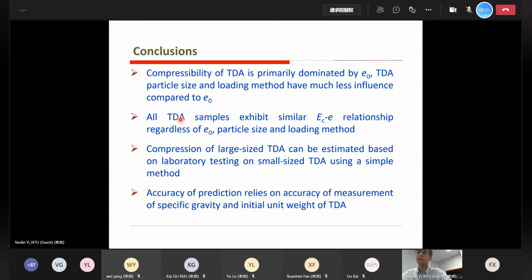And second, all the different types of TDA samples we studied have almost the same compression modulus and void ratio relationship, regardless of initial void ratio, particle size, and loading method. So this is very useful for practice. We can use this to estimate the compression of large-size TDA based on the results of small-size TDA in the laboratory. So it's possible to apply this method for design.